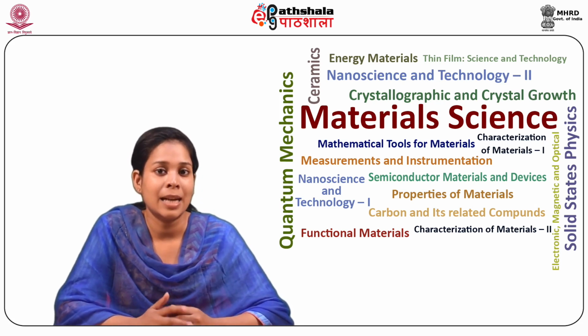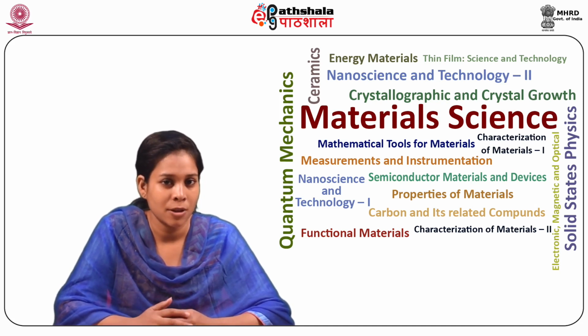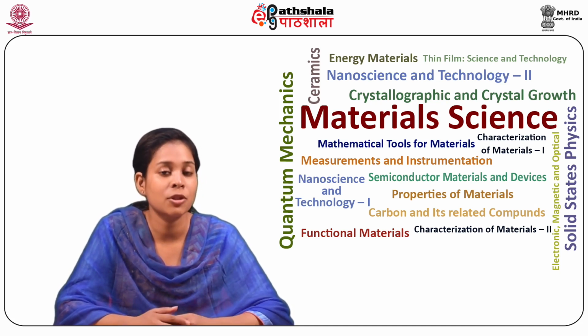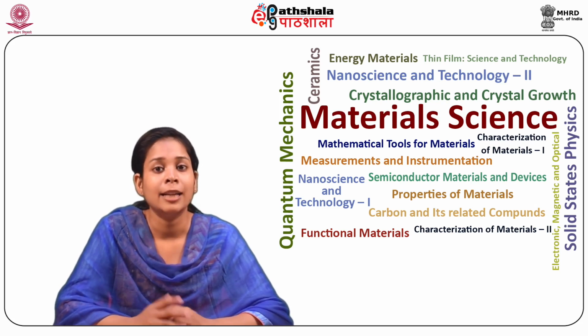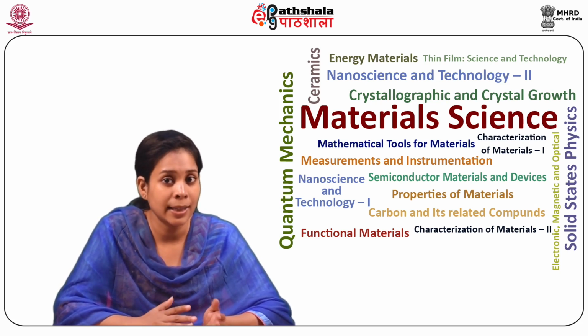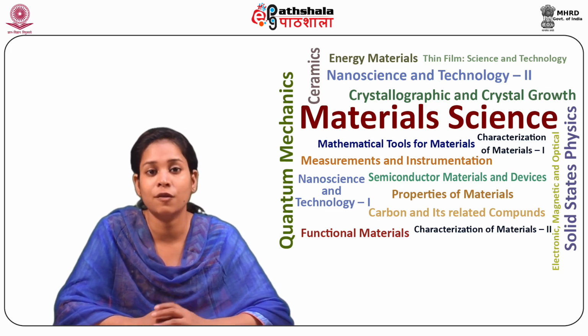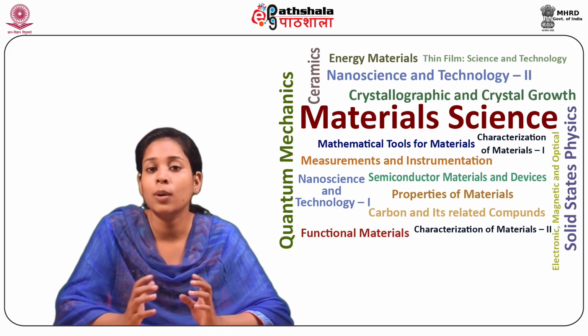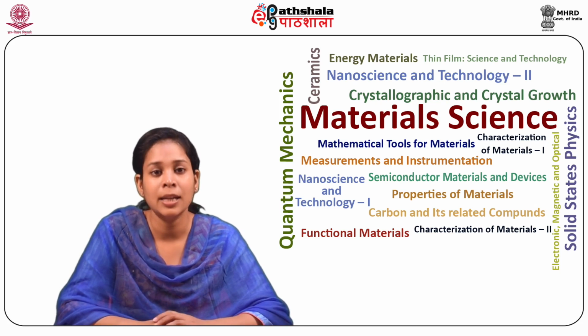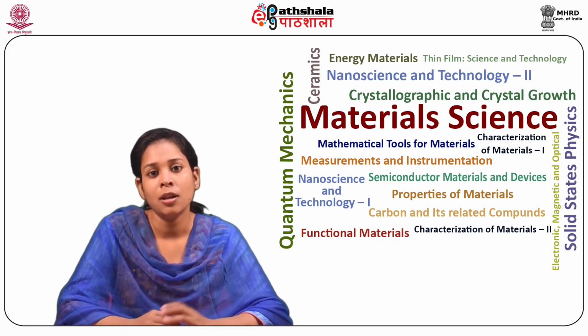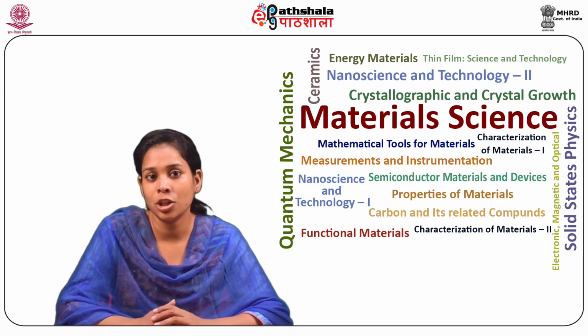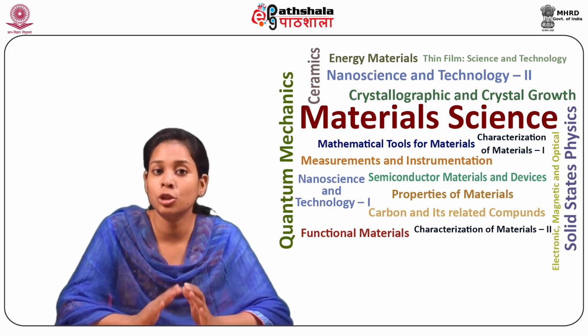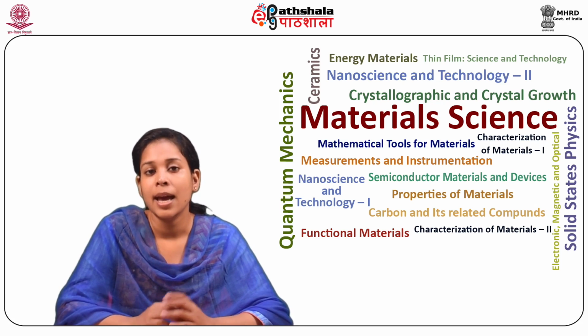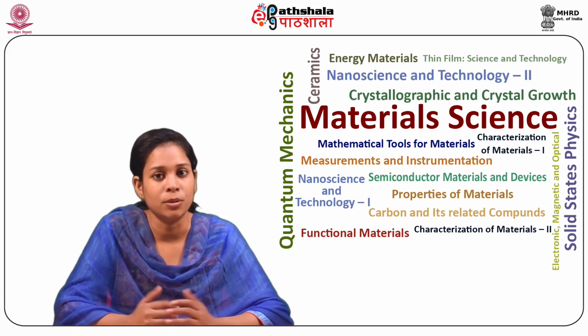In the silicate glasses, we have learned that besides the glass formers, there are other elements which are also present, and when an oxide which is not a network former is added to a network forming oxide, some of the oxygen remain unbonded to maintain the coordination of oxygen at 2 or less according to the Zachariasen rule.